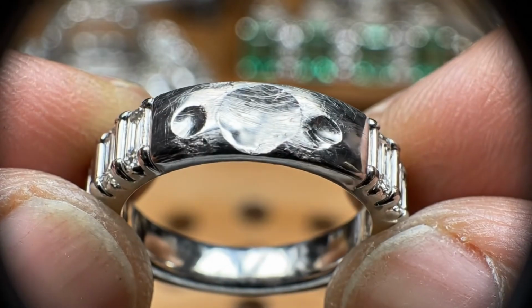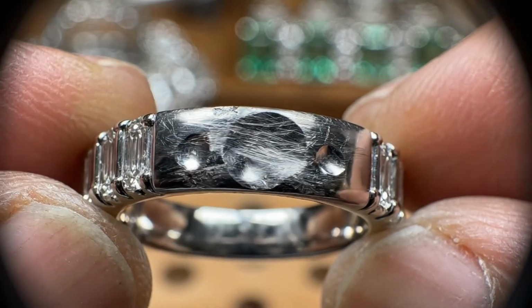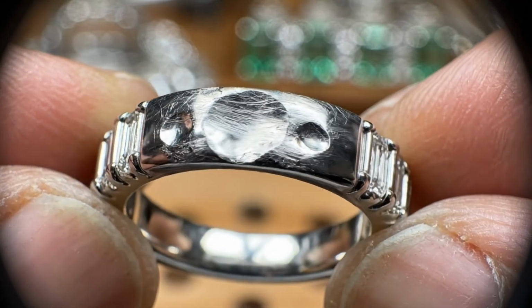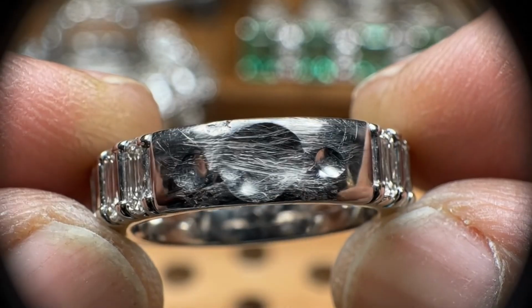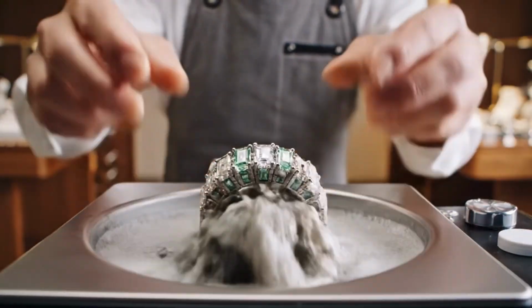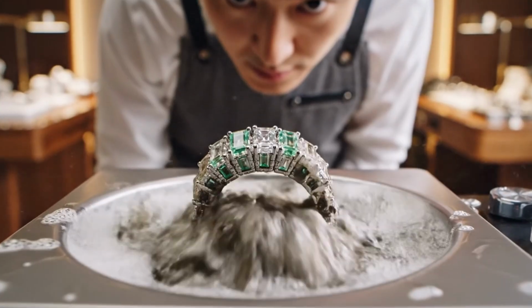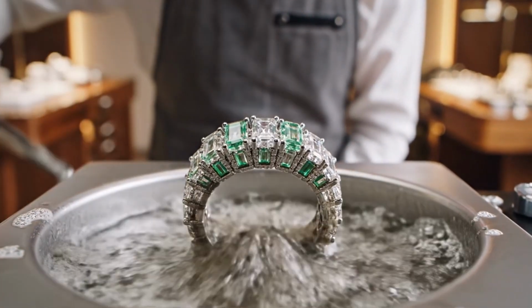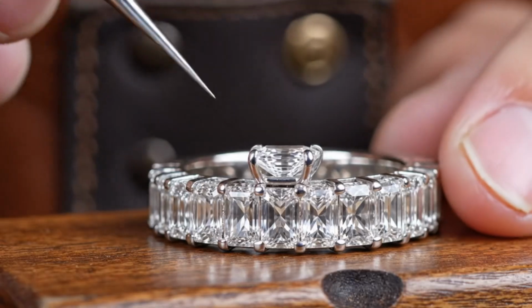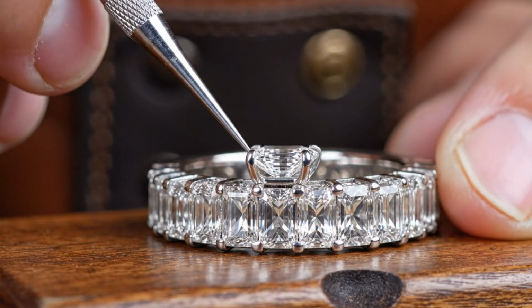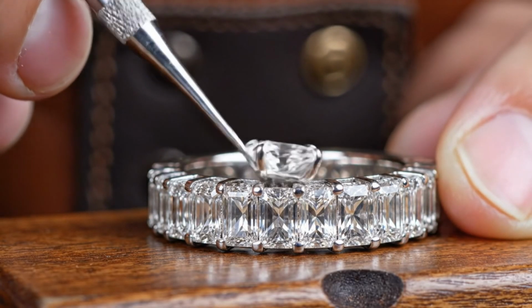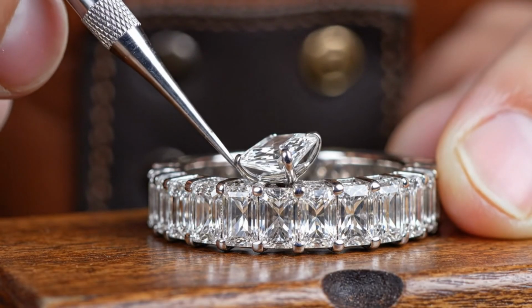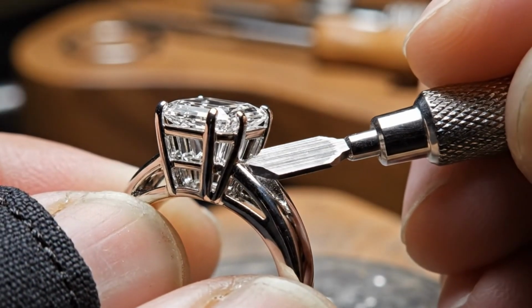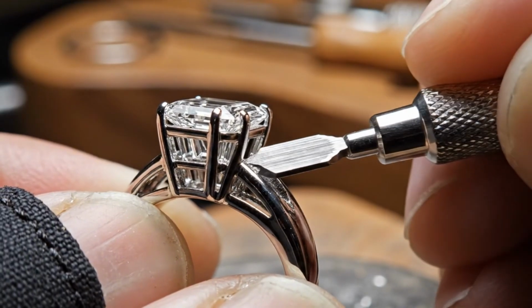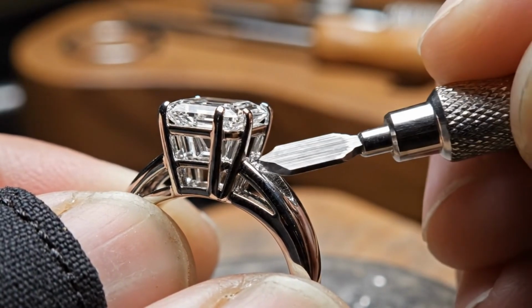We inspect the bottom of the shank under magnification, noting the heavy displacement of platinum caused by gripping hard surfaces like door handles. The ultrasonic bath is prepared with a stronger solution today, needed to break down the hardened layers of soap and lotion residue. We notice a slight movement in the seventh stone, a common result of the metal ring flexing slightly during months of regular wear. The graver pushes the metal back against the diamond girdle, tightening the setting until the stone is once again completely rigid and secure.